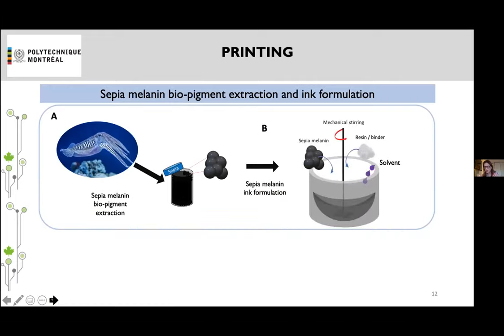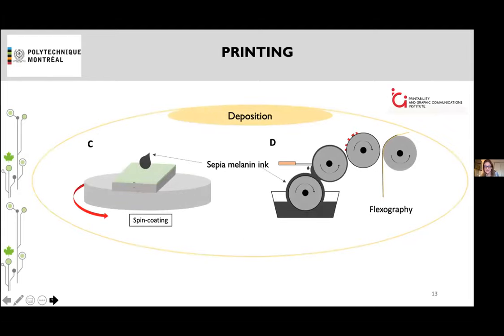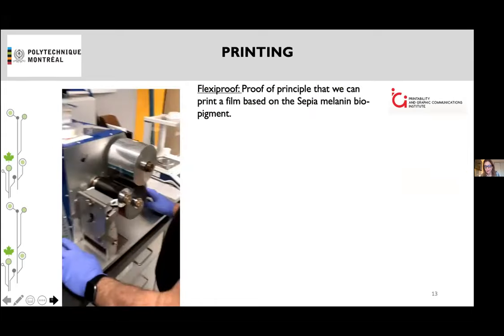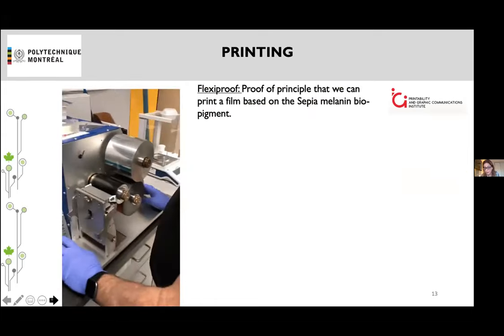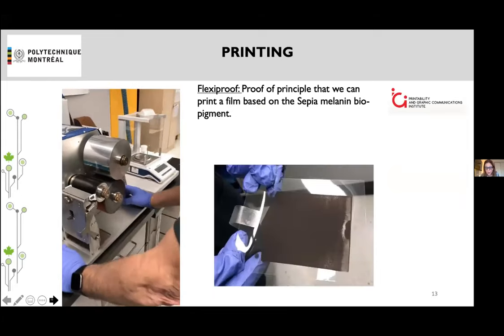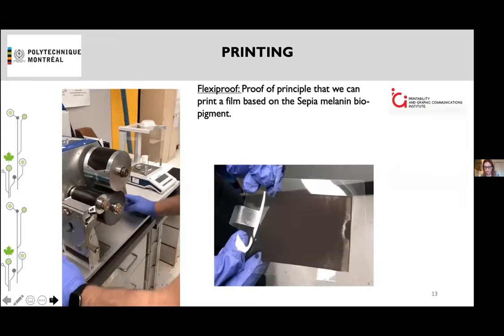Anyway, to prepare the ink, we have to add these binders in a way that the ink can then be introduced in the flexography setup that I will show you in a few seconds. This could be scary in the sense that these binders are insulating. And so we could think, hey, we are diluting the conductive particles within a sea of insulating matter. So we wouldn't be so happy to do this. At the end of the day, truth is that we deposit our layer kind of easily after addition of this insulating binder.